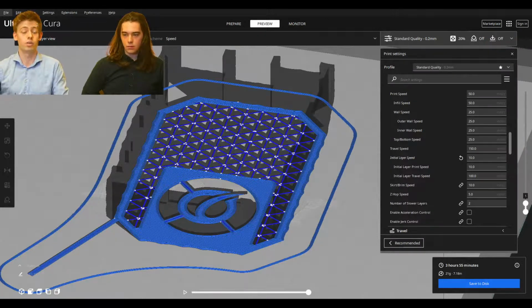And with heated bed, with other beds, having bad adhesion to the bed is probably the first cause of bad first layer problems. Could have said that better. But yeah, when material comes out of the nozzle and the material is too cold, it doesn't stick to the bed. So when you're printing really slowly, that makes sure that that material actually reaches the nozzle's temperature. And especially when you're printing really thick lines, then you might actually get close to your volumetric flow rate if you're printing at normal speed. So you have to print slower than that just so that you can pump out a lot of material per second and a lot of heat per second so that stuff sticks to the bed really well.